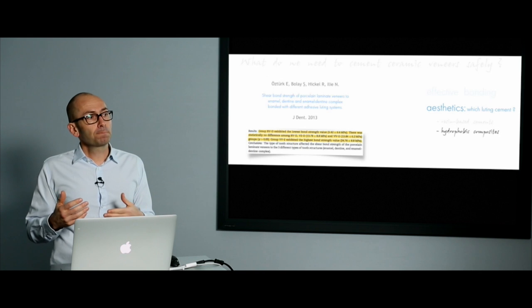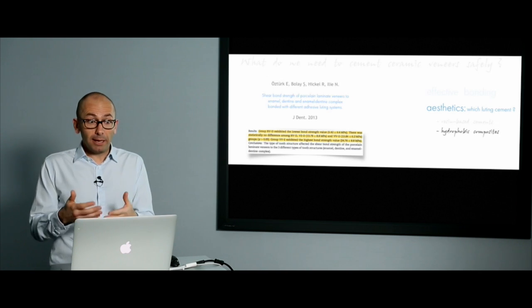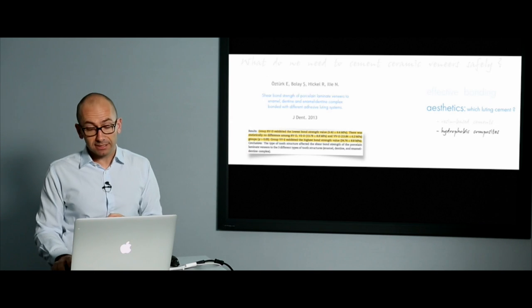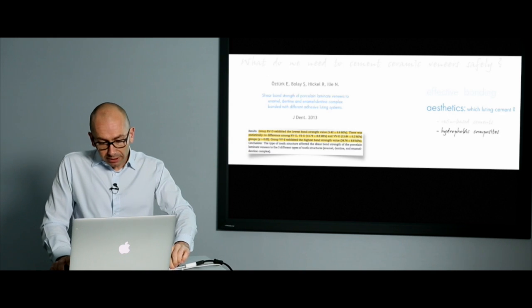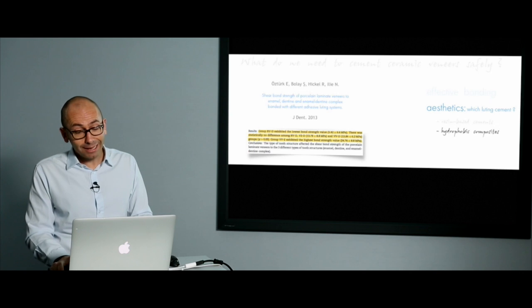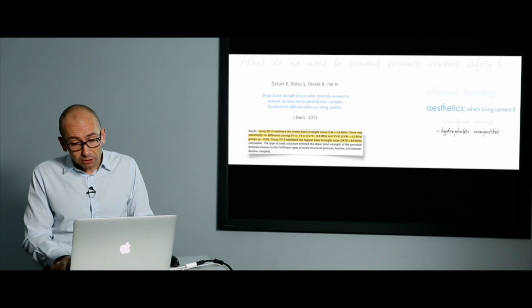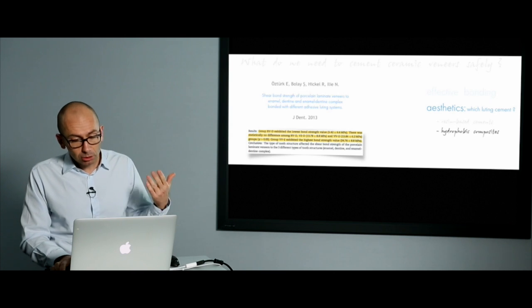No ionomer, no resin modified, never. But then, you've got a lot of different ones. So which one to choose? Because you know, the manufacturers know that this is a very difficult procedure, so they've tried to facilitate this procedure, and they introduced in the market 10 years ago, 15 years ago, some new products. It's resin actually, but it's quite a hybrid resin with hydrophobic component in it, very classical, and also hydrophilic component in it, just to allow you to handle it as easily as the conventional cement. But it does bond because it is resin. Unfortunately, those hybrid products, which are also called the self-adhesive cements, are not that performant, and are not that aesthetic. So I wouldn't recommend you to use those products, and prefer, please, the hydrophobic, very classical, conventional composite.